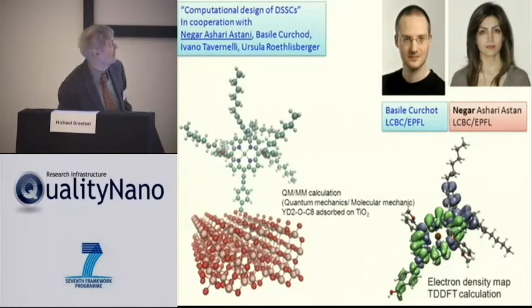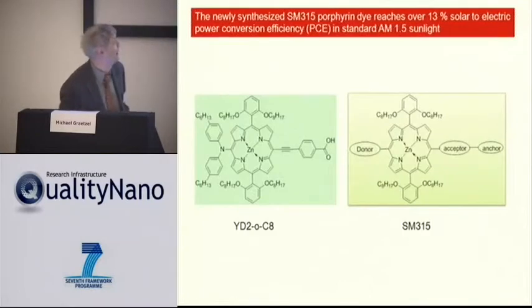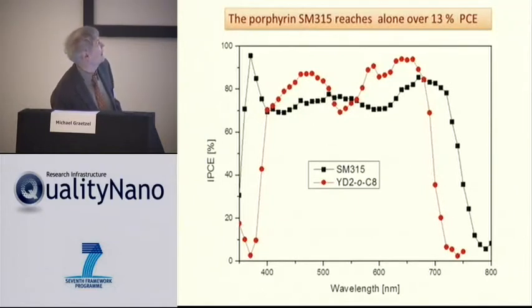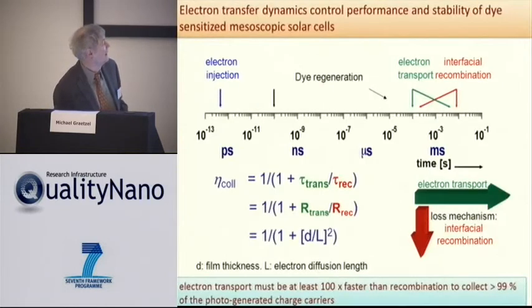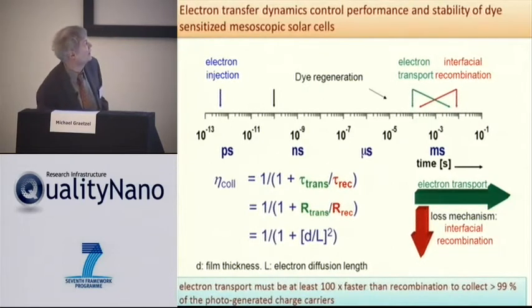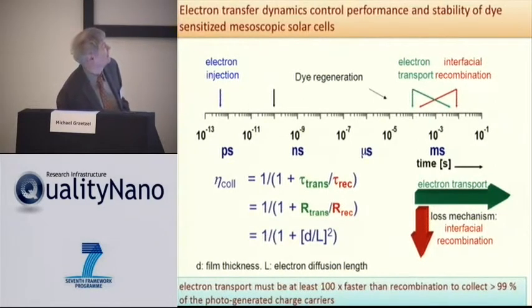And out come these dyes that have now reached, recently with a slight modification of the dye structure, a very good coverage. You see, the black is a new dye. It absorbs all across the spectrum and it generates current with high yield all across the visible, starting from 750 nanometers. And so we can say we are collecting all the electrons that are being produced. The electron transport time is much faster than the recombination time. If you have that, then you can collect over 99% of the carriers.